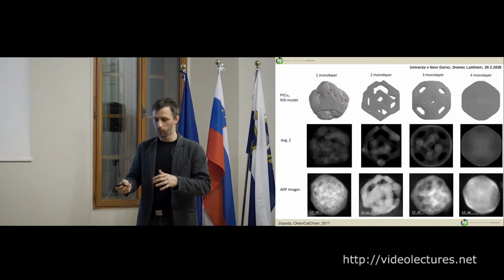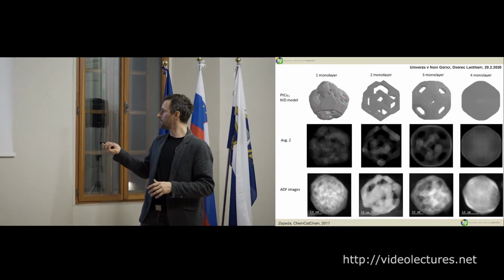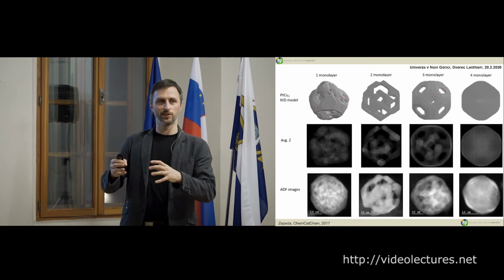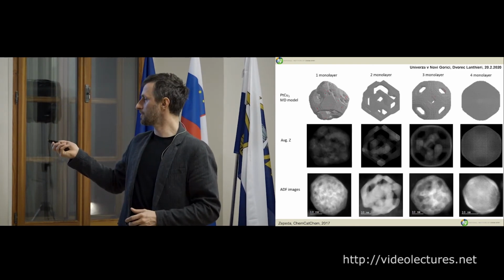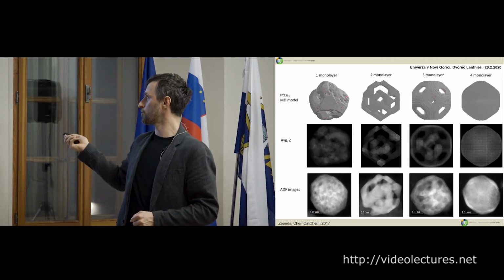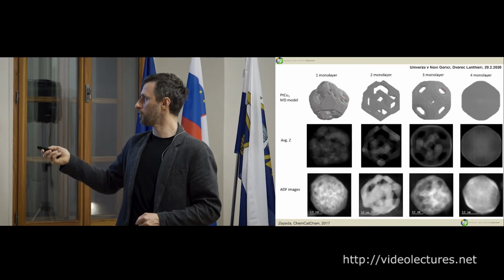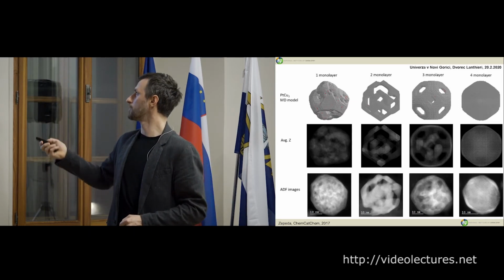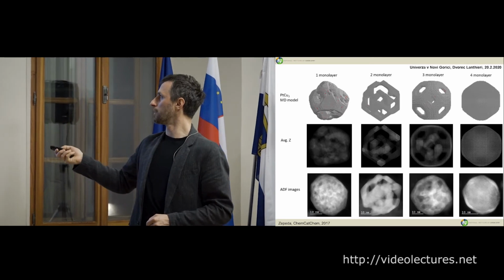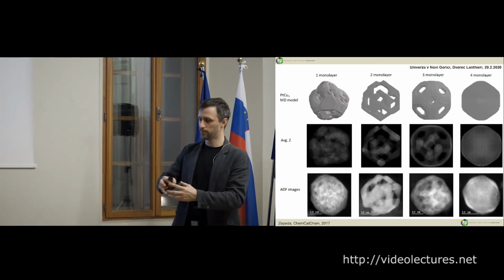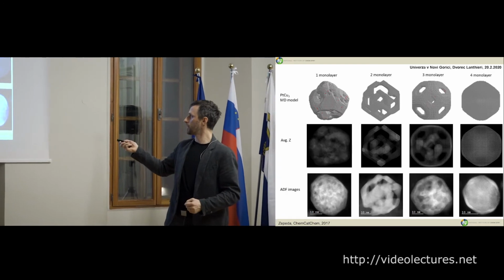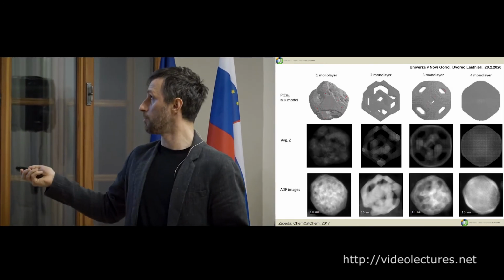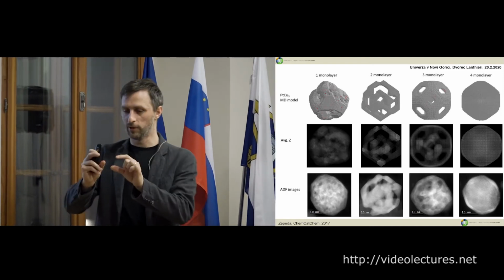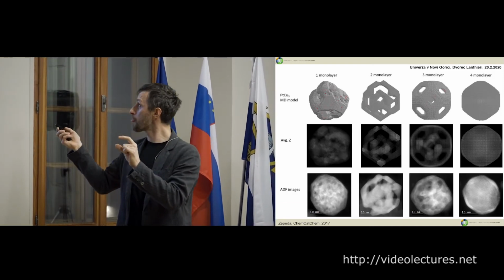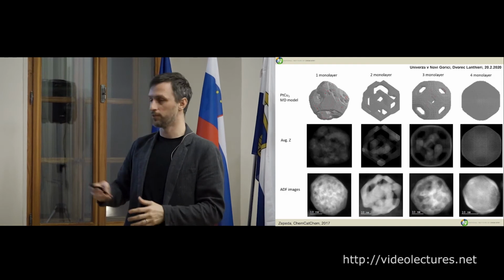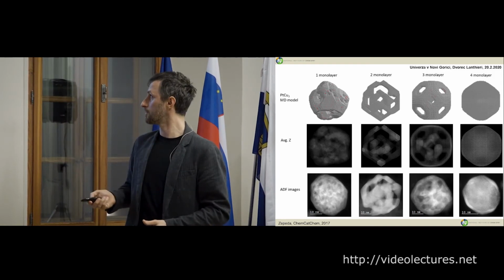So, and how we model this is that we put more monolayers of platinum on the surface. So if you run this model, you don't get pores, you just shape it. Yeah? But if you have just one monolayer, you get pores. And this is again shown here. And this is when we make these images look like TEM images, and this is then the real TEM images. So the amount of surface monolayers of platinum can affect if you get the dealloying or not, so pores.